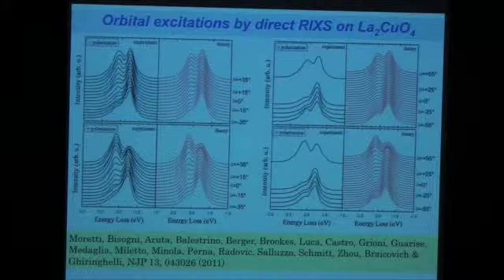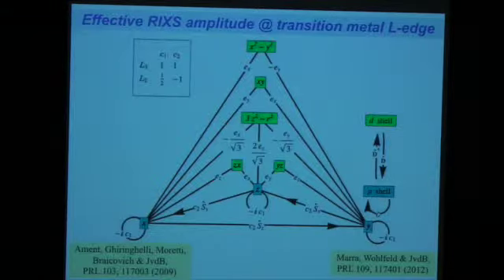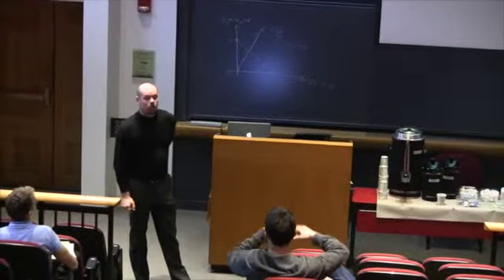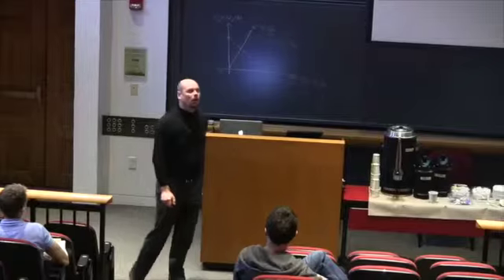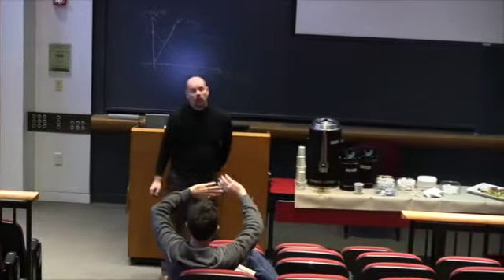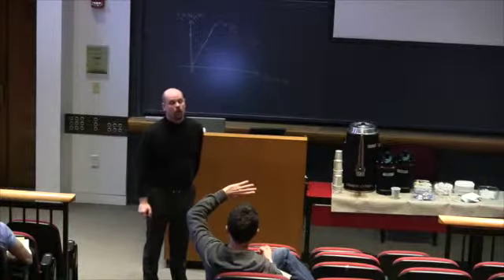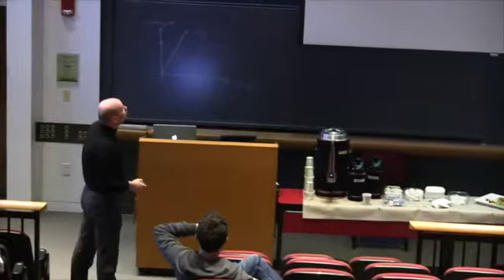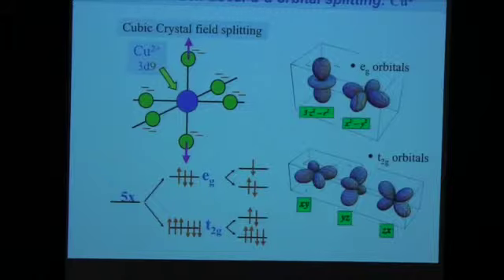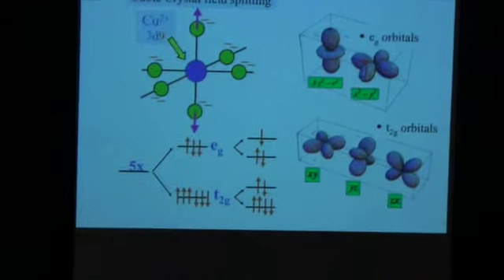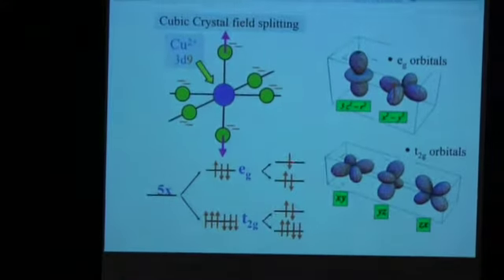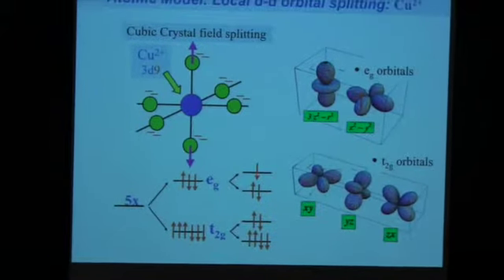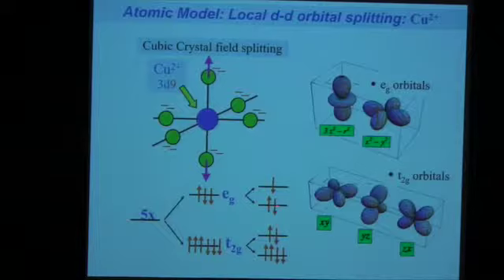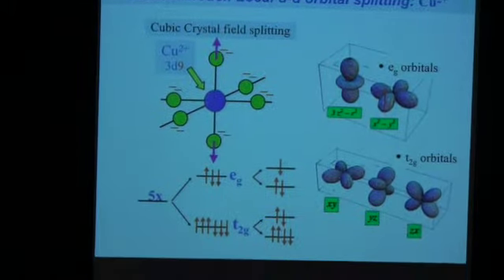Does this work? Well, here are the D states. So this way you're going far away from a single band model, from the cuprate model, because you're saying that you really make an excitation when the hole left behind is in some very low-lying orbitals. The EG orbitals are below the T2G, and now you're saying that the hole left behind after you refill the core state is in one of the EG orbitals, and is it still? No, okay. So I'm saying I didn't draw the core. Now if here is my core, I have 2p. I come in with an electron. It has to go here in x squared minus y squared. Right? And I'm saying I just showed there's the amplitude for getting now this electron here, or this up electron filling the core. So, okay, so it's still EG, but it's a lower-lying EG. Right? Yes. So at least single band cuprate model.